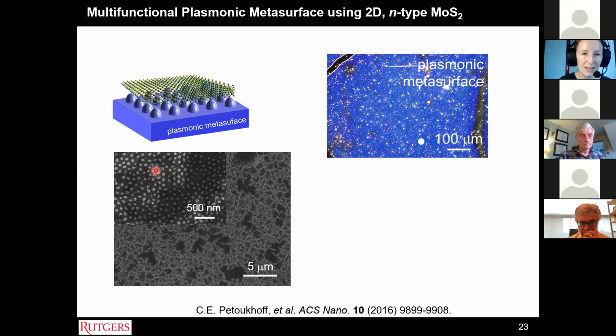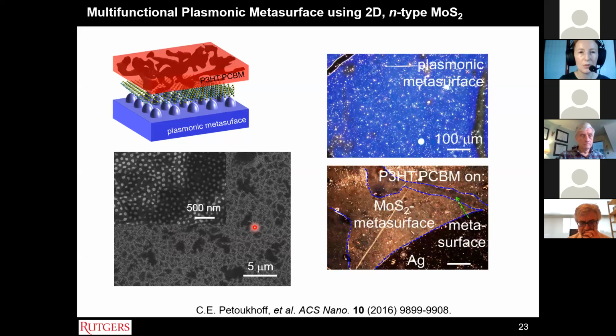You can see there's partial coverage. It doesn't fully cover the structures. It's not fully conformal, which is one of the disadvantages of using these types of 2D materials. However, it was quite successful in terms of improving the electronic properties and the absorption in the P3HT.